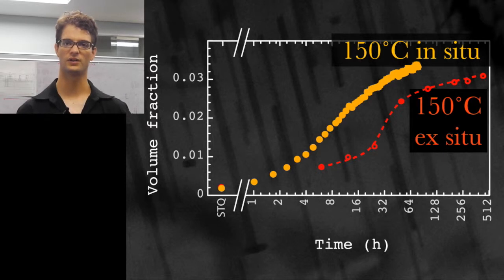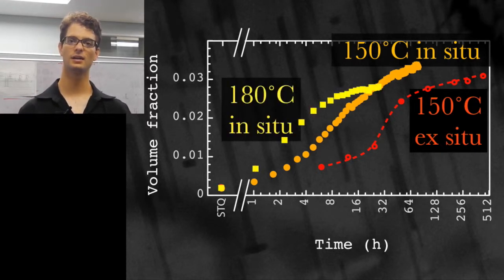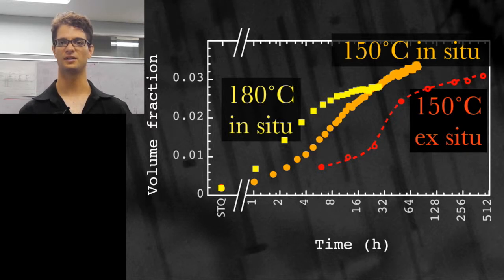With a one hour time resolution, we can follow this precipitation process over the course of several days. We can then easily increase the temperature and see how this affects the precipitation kinetics.